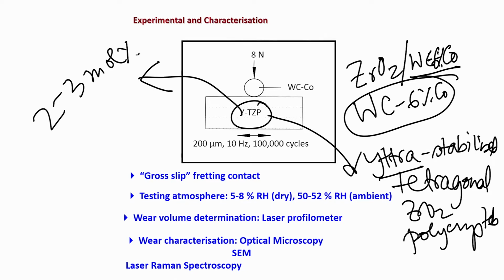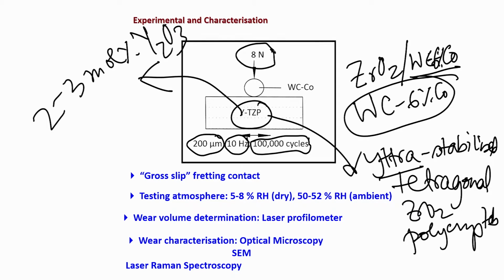Okay. And why tetragonal? Tetragonal means by adding 2 to 3 mole% yttria to zirconia, we are able to obtain phase pure tetragonal zirconia in this particular case. That means that the microstructure is fully tetragonal phase. The linear displacement is 200 micron, 10 hertz is the frequency, and 100,000 cycles is the fretting duration. Why this load? Because we have done several other initial tests, but we have found that 8 Newton load is good enough to cause very severe deformation and wear at the fretting surfaces. And this particular combination of parameters also allows us to ensure gross slip fretting contact.